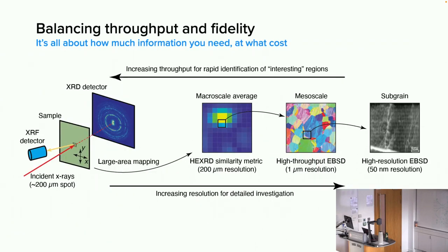So really, one of the points here is that, again, you have to balance your desire for throughput and your need for fidelity of the measurement. And really, the right way to think of this is not EBSD versus X-ray diffraction. It's that X-ray diffraction can provide a very low fidelity but very rapid test at very low cost, whereas EBSD, particularly if you're doing high resolution EBSD, is a much slower technique, therefore it costs a lot more in terms of time, but provides you with a much richer set of information.